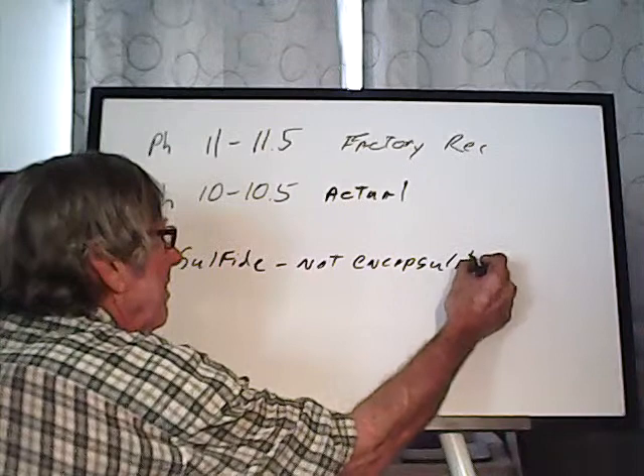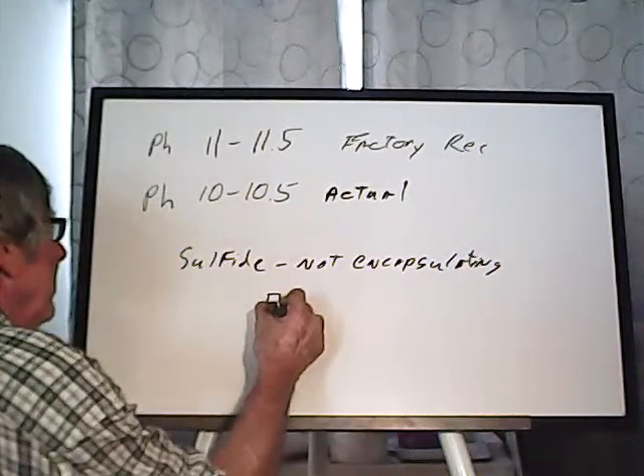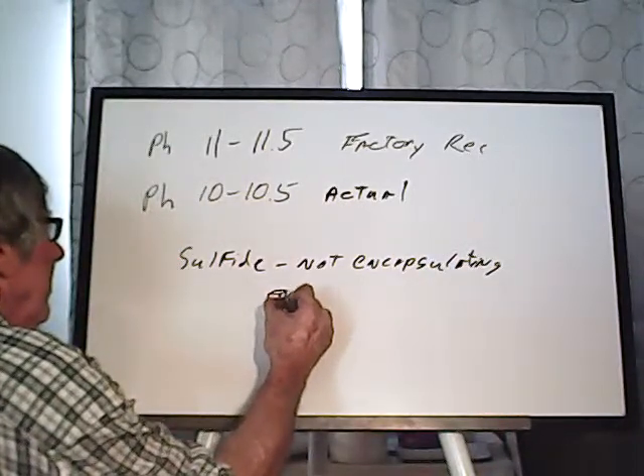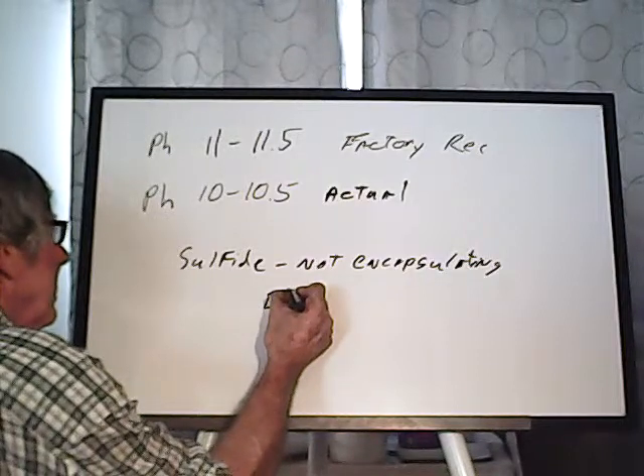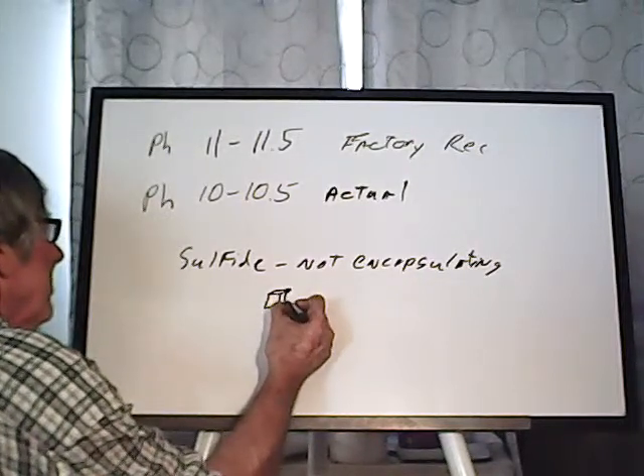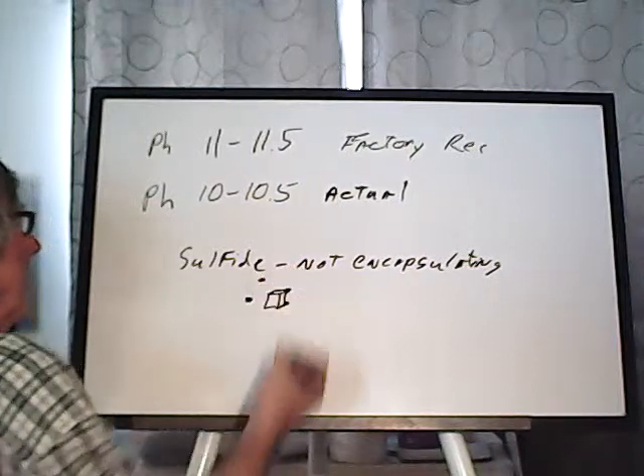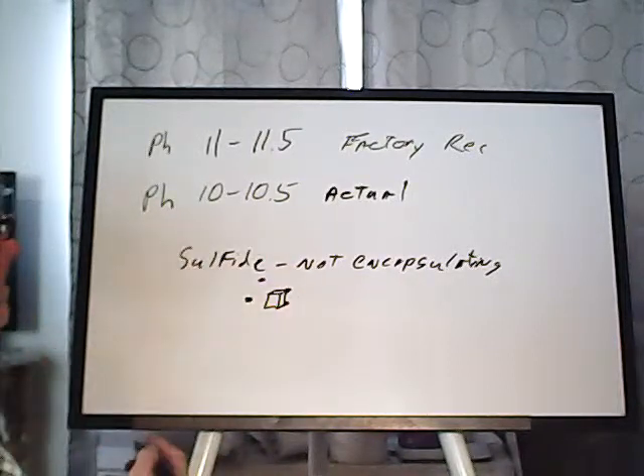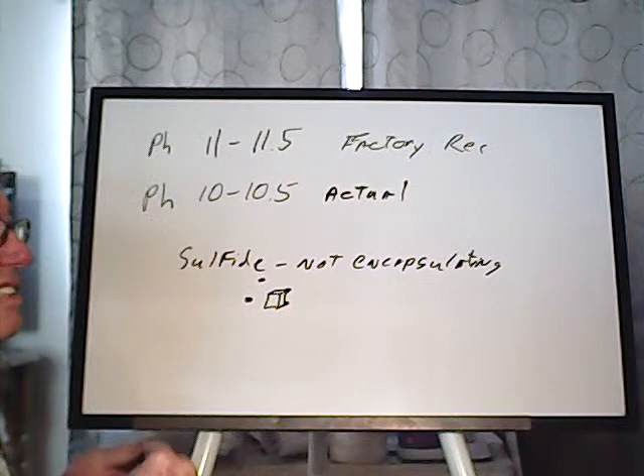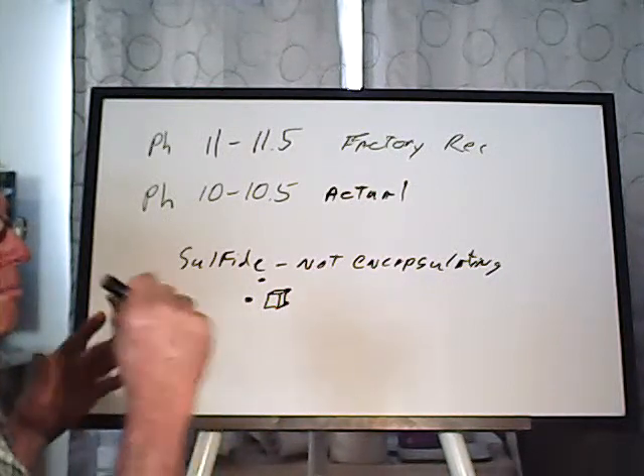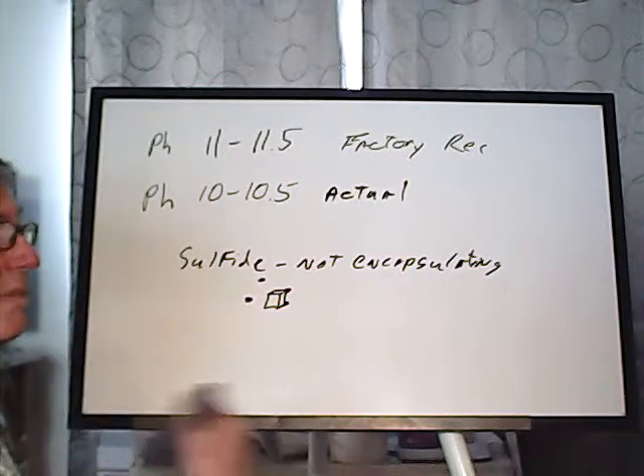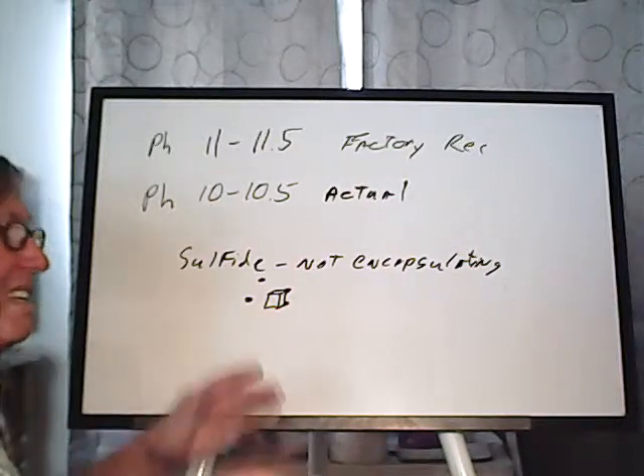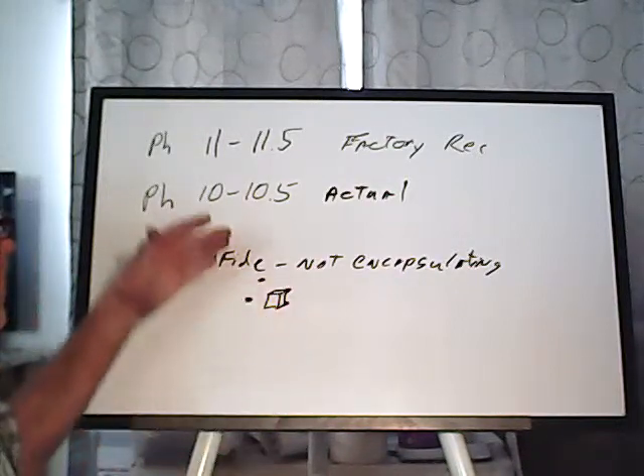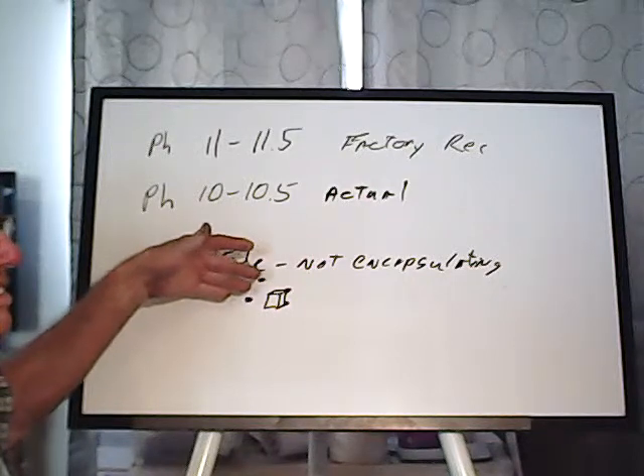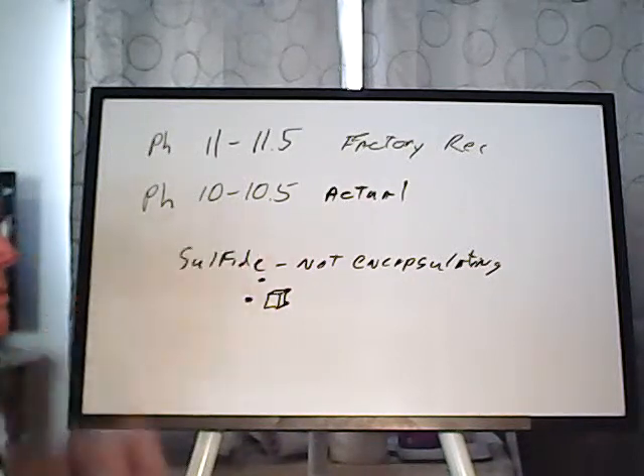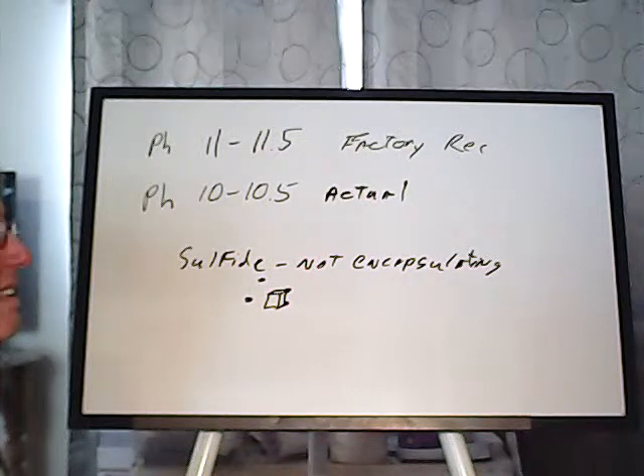By that I mean, here's your little pyrite cubes, and then the gold is either on the outside or separate. Now, in this case, you're going to have more reagent consumption because that sulfide is going to react with the hydroxide and it's going to be tending to neutralize it. But as long as you can keep your pH in the same situation, you're probably going to be able to dissolve your gold reasonably well.